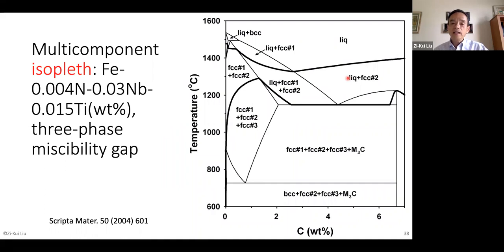The interesting thing here is that we see a 3-phase miscibility gap. We have 3 FCC phases. We have the regular FCC phase, that's the disordered FCC. At high temperature, this one is titanium nitride, which precipitates from the liquid phase. And at low temperature, you have niobium carbide. So 3 FCC phases coexist in the structure.